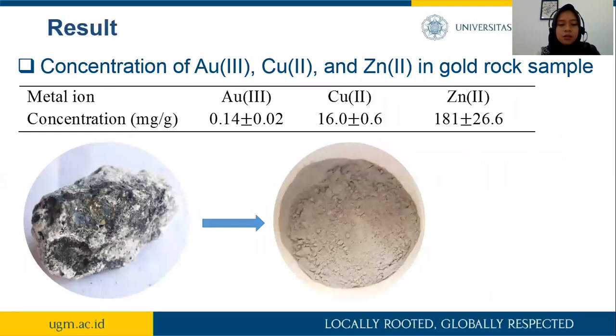And the second analysis, of the metals gold, copper, and zinc in the leaching solution, was performed with the standard addition method by AAS. The content of gold was the smallest, around 0.01% in the sample solution. The method that can be used to purify gold is selective adsorption, adsorption with a material that has active sites of amino groups in our adsorbent.